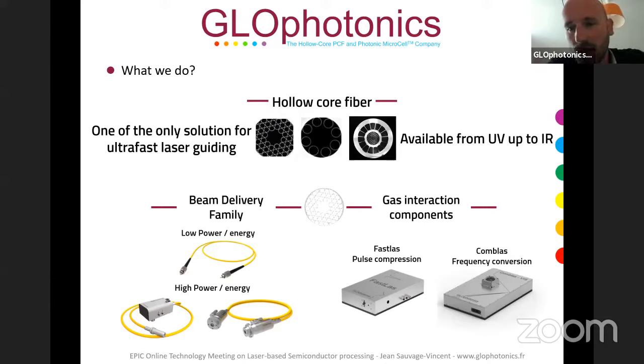So one of the solutions is to guide the laser via a specific fiber, and the hollow-core optical fiber is one of the only solutions for ultrafast laser guiding. In one of these geometries of fiber, so you can see here 2 kinds of geometry. This one is called the Kagome fiber. The other one here is called the single ring fiber. You can guide light like an ultrafast laser, like Amplitude, like Coherent, and other partners, through this fiber. And you guide only in this core here. The structure is here just to constrain light to stay in the hollow core. And if you constrain light to guide in the hollow core, you can put a lot of energy, a lot of power, and you can guide an ultrafast laser without disturbing the pulse. You will not increase the length of the pulse, and you will keep the laser pulse from the input to the output safe from any deformation and so on.